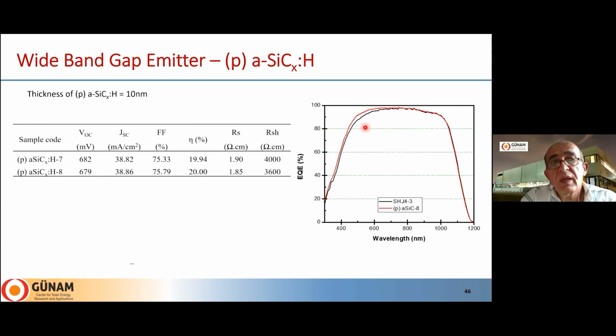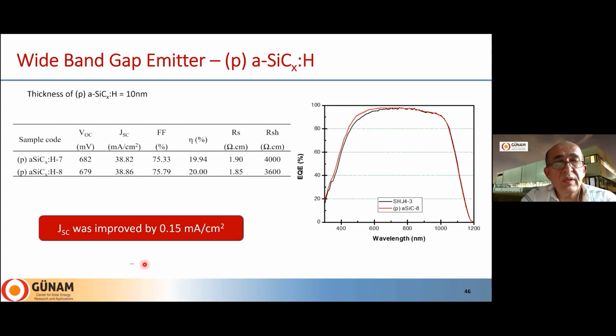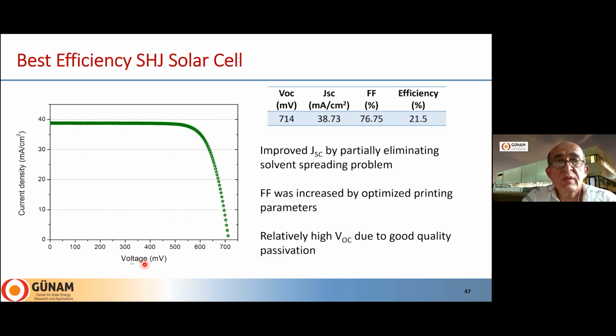And you see clearly that the blue part of the spectrum, that means the front side of the solar cell, was very much improved by using silicon carbide. So the short circuit current was then improved by 0.15 milliamp per centimeter square. The best solar cell is shown here from our standard heterojunction solar cell studies. So we have reached values above 21%.